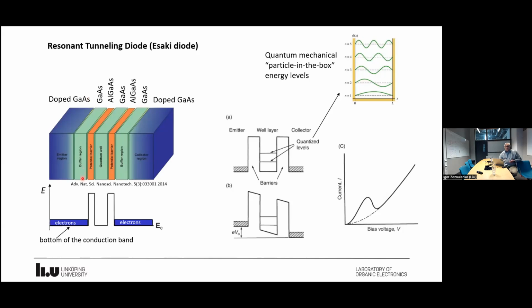The difference between them is that, in this energy diagram, I plotted the bottom of the conduction band. And you can see here that the bottom of the conduction band of aluminum gallium arsenide is higher than that of gallium arsenide. This means that this material would be a barrier for electrons which are residing here in the gallium arsenide region. Okay, so what happens here? You have the electrons here, and then you have this double barrier with empty space.